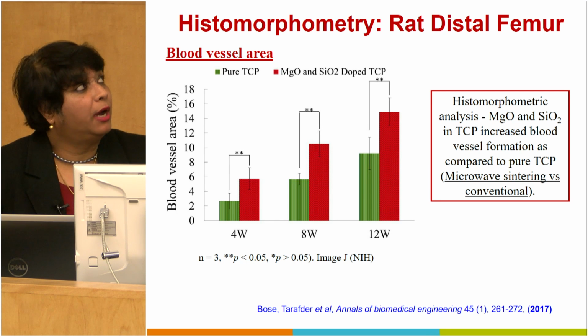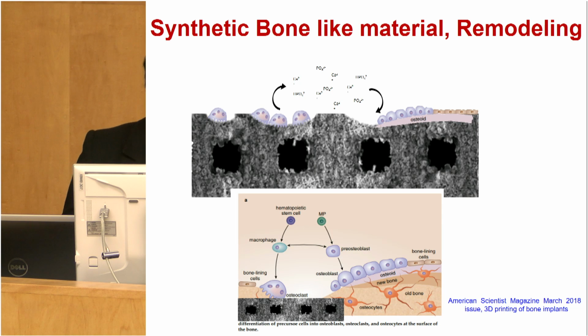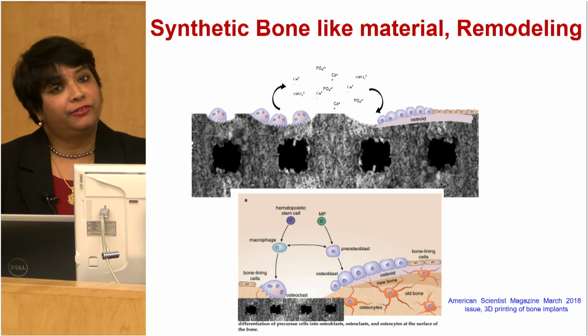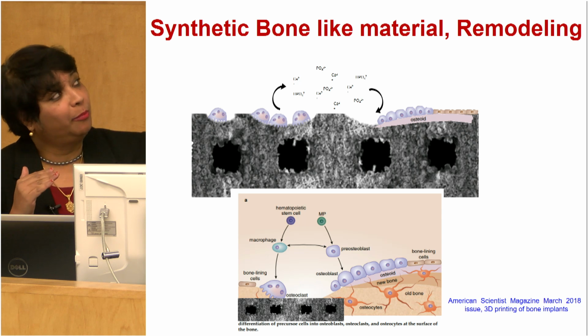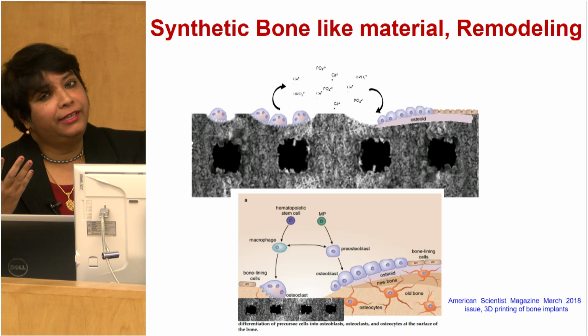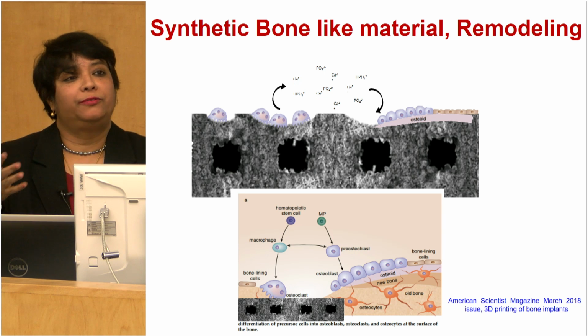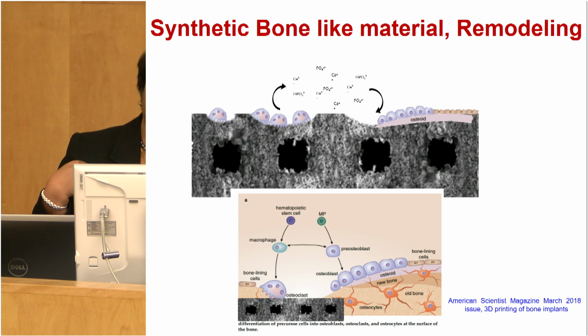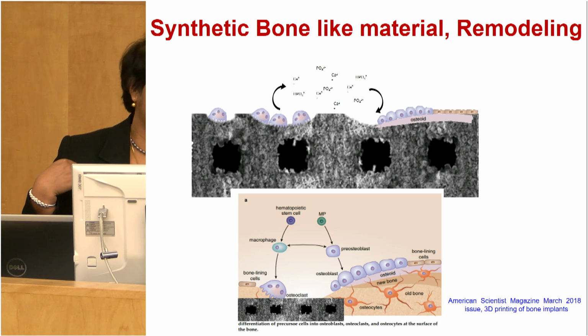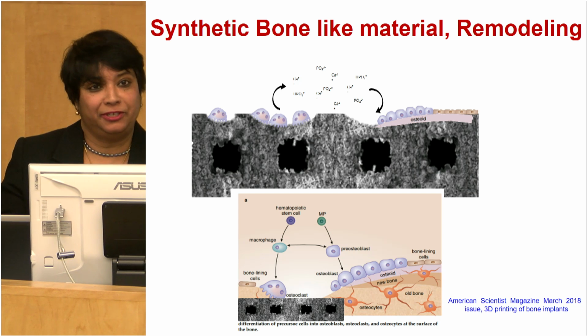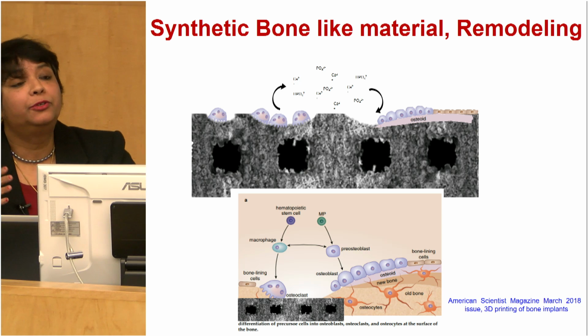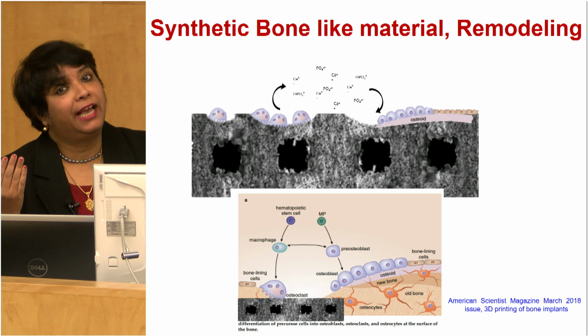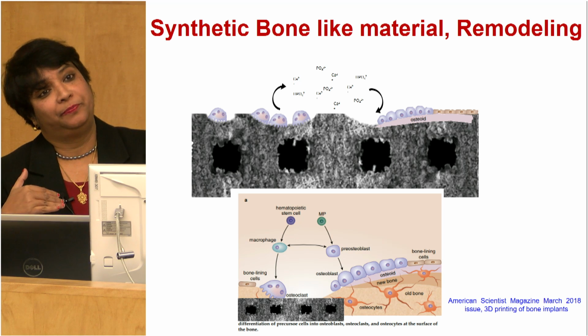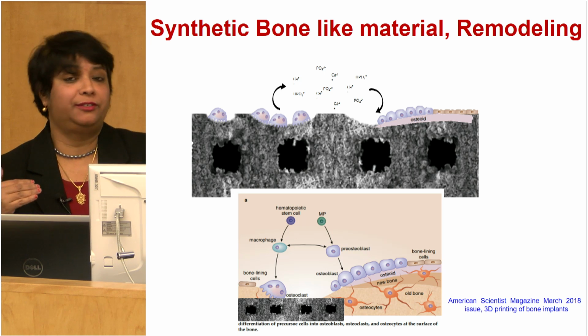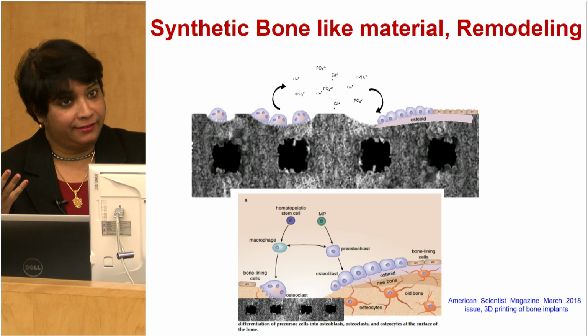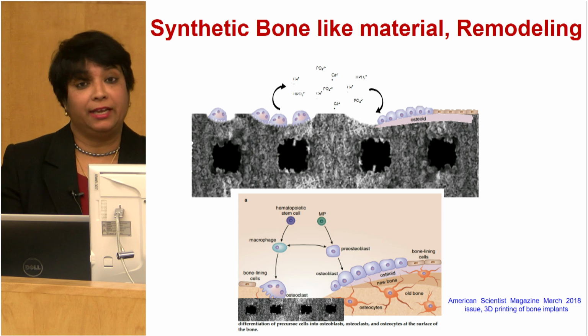I know that I told you what happens at the cellular level. So just to connect the dots, here is what happens at the materials level. What you are seeing on the top part, the calcium phosphate based porous scaffold, is called the dissolution precipitation process. What does it mean? Our body is actually the best corrosive environment. We have a 37 degrees centigrade body temperature, and we have salt in our body. Salt and temperature corrode the material, whether it is metal or ceramic. So ceramic material dissolves in the microenvironment and also precipitates back to form new bone, as the osteoclast bone eating cell and osteoblast bone forming cell work together. So there is cellular level activity, and there is chemical level activity in terms of bone remodeling.